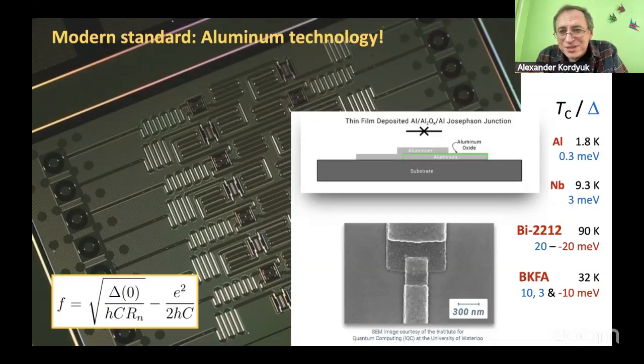This Tc defines the superconducting gap, and for this gap, the frequency at which qubits communicate with each other is in the microwave range. And it is comparable to these low temperatures. One of the solutions is to increase the superconducting gap by switching to other superconductors. Of course, there is a technological issue, but it appears that it is also a principal, physical issue, because we could do it.